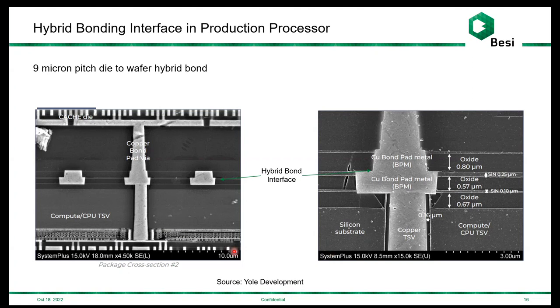And this is more of a close-up view of what the hybrid bond looks like after bonding. You can see the through silicon vias here on the back. This is the compute tile. So you can see the transistors, the back-end line routing, and then the TSV connecting to the via middle structure through the back of the die. The hybrid bond pad is formed on the back of the die with an oxide layer there. And then the top die with a copper via through the passivation.